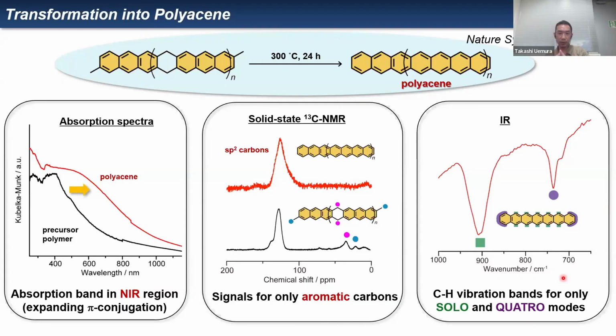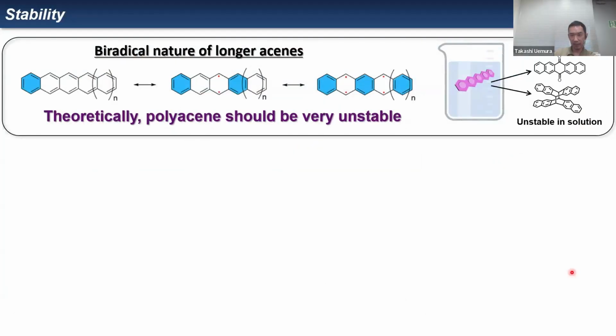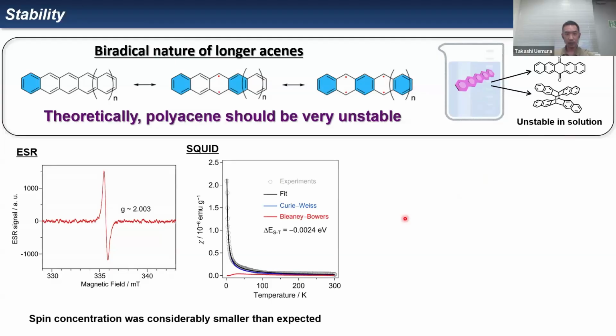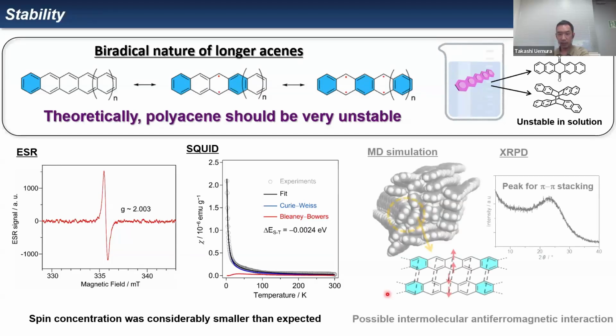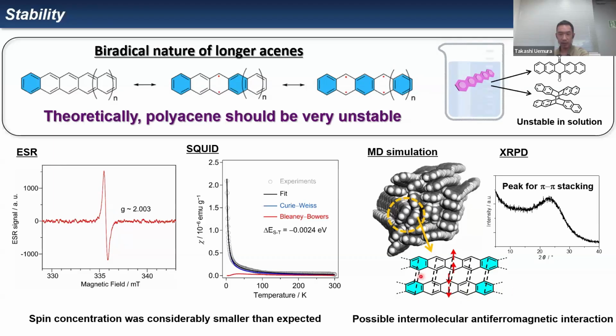So now we're happy to say that we could obtain polyacene, but here I'd like to remind you of the stability of acene. Theoretically, polyacene should be very unstable because of the biradical nature of the longer acenes, and actually even pentacene is unstable in solution, easily oxidized or dimerized. So here we checked the ESR and SQUID of the obtained polyacene and found that yes, the polyacene has biradical nature in this system also. But actually, the spin concentration was considerably smaller than expected. This would result from the intermolecular antiferromagnetic interaction among the chains like this, as was suggested by the MD simulation and the XRPD patterns.